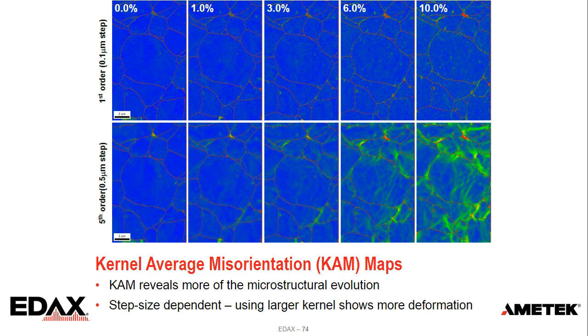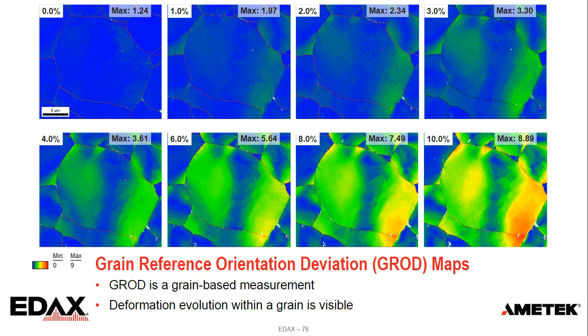So when we're looking at these point-to-point misorientations, it can be very dependent on step size and the size of the misorientation gradient. Again, if our step size measures things with a finer precision than we can measure, we'll see a little bit more blue. So that's why we can expand the size of these kernels to see the misorientations more clearly. And then we could use something like our GROD maps to show a grain-based measurement. So we see how that particular grain we're focused in on sort of bends and evolves as a function of strain.